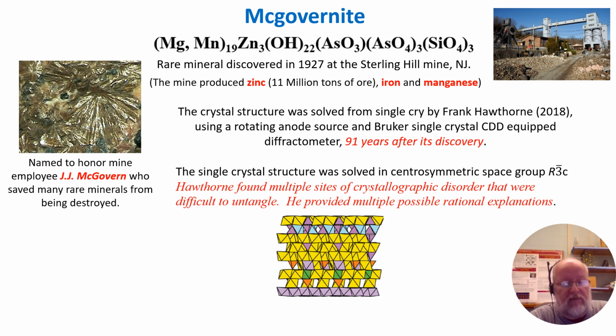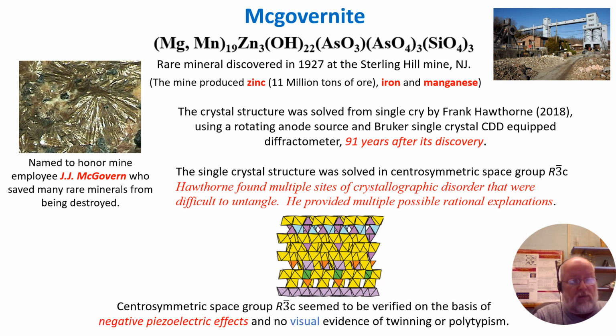This crystal structure remained elusive for 91 years until it was finally solved by a Canadian crystallographer, Frank Hawthorne, in 2018. He was able to solve it in the centrosymmetric space group R3-C and describe the structure as having multiple sites of crystallographic disorder that were difficult to untangle. He provided multiple possible rational explanations for this disorder. His work was supported by previous work when investigators determined that the Mcgovernite had negative piezoelectric effects, which indicate probably centrosymmetric.